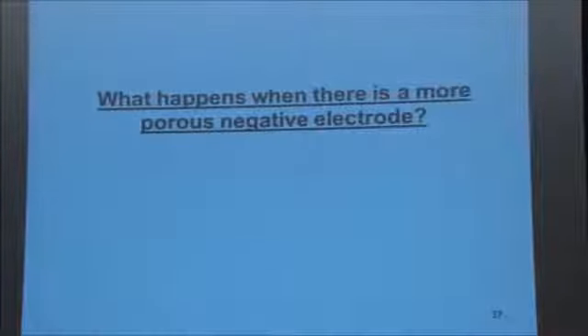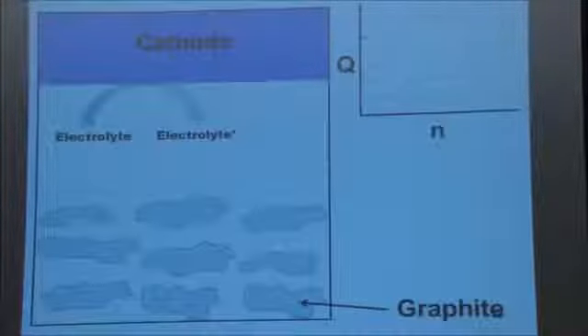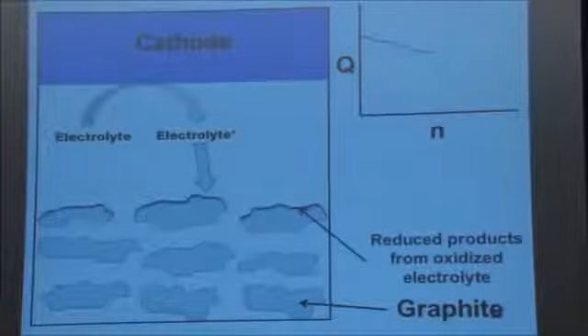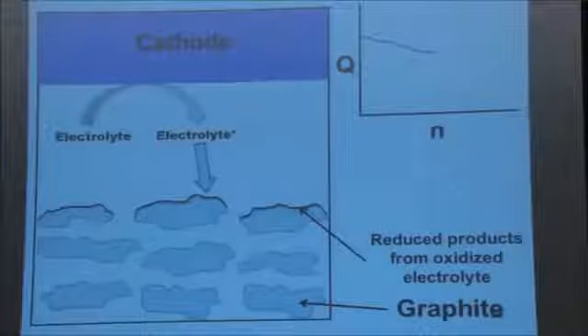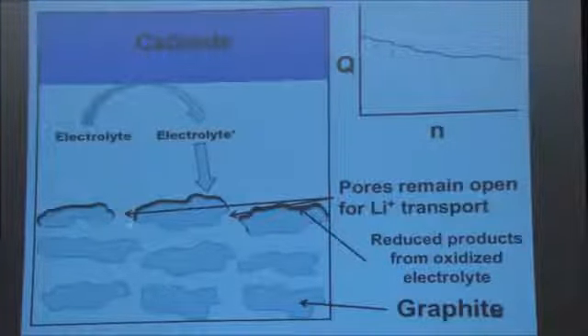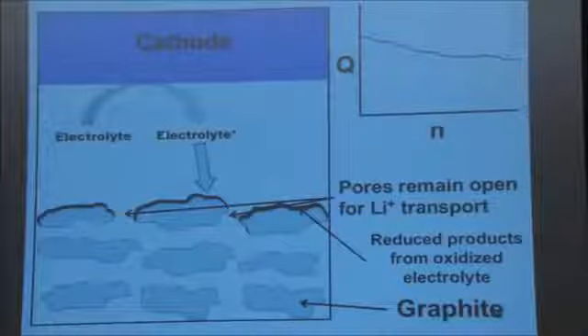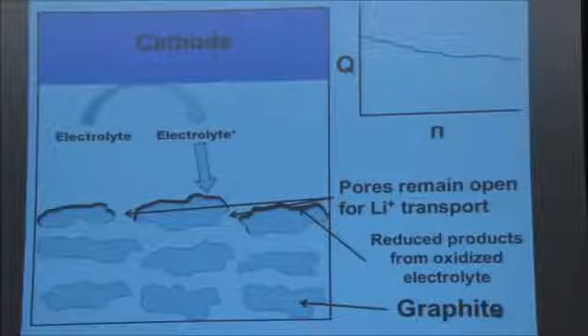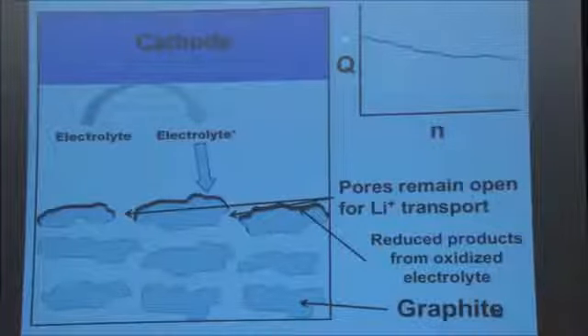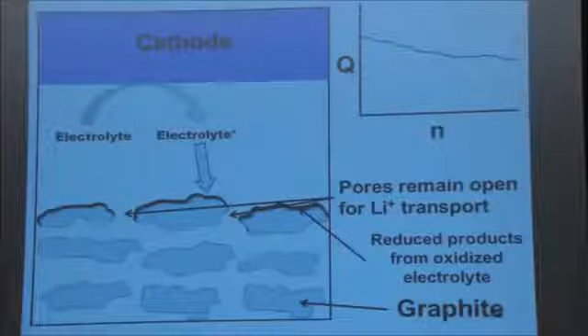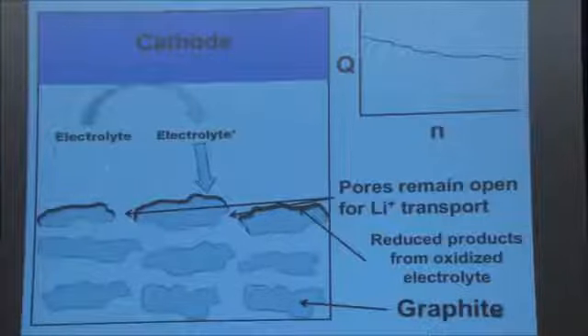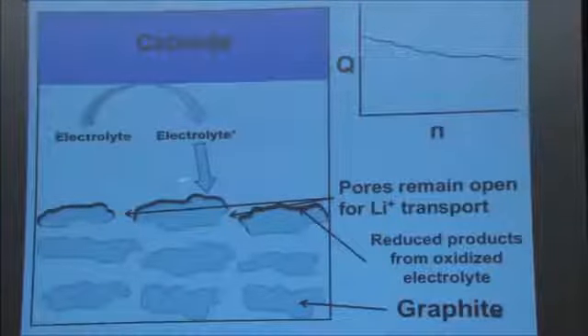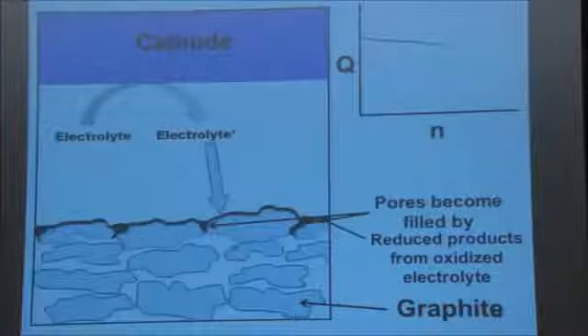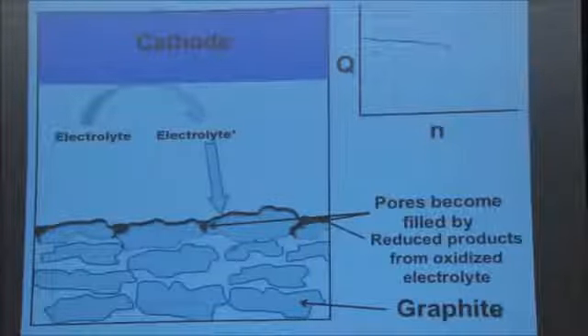If you had a more porous negative electrode, what would happen then? Well, you get the same scenario happening, but the pores don't close. And if you make the same cells with less compacted negative electrodes, they don't show the catastrophic failure. The failure looks like this, okay? But it's still bad for the electrolyte oxidation that's going on because you're losing electrolyte. Okay, so let's go back to our scenario.